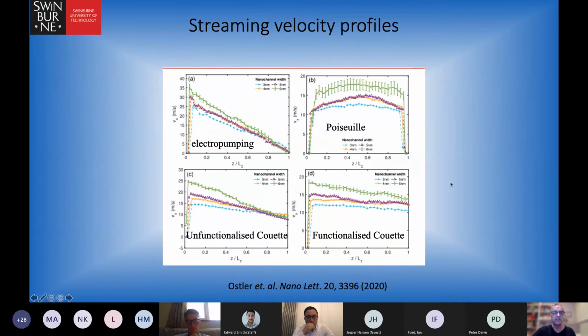Just a quick snapshot of the types of profiles that we get. This one is typically what we get with electropumping for different nanochannel widths. For Poiseuille flow, remember we've got water confined to graphene, so that's a very hydrophobic system with very, very high degrees of slip, as you can see from the velocity profiles for the Poiseuille flow. We've got unfunctionalized Couette flow and functionalized Couette flow as well.